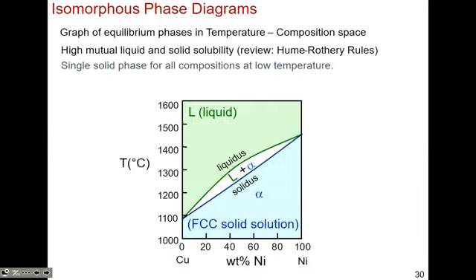Okay, so I've summarized basically all of that. You have one component, let's say call it copper. You have a melting point of copper at about 1,100 C, say. You have the melting point of nickel. That is much higher, it's about 1,450 C. When you start mixing them together, I can tell you how much I mixed if I just tell you this binary phase diagram, and I say, look, if you add in 20% of nickel, and you're at 1,200 C, or maybe let's make it a little bit more egregious, let's say 1,150 C, you're going to be right there.